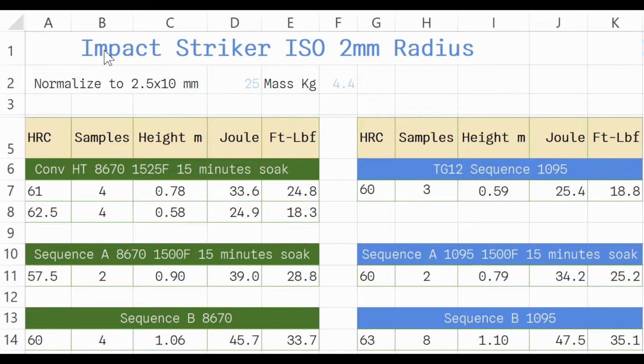I fixed the vertical impact toughness tester. Now it's using the striker, which is a carbide head with ISO geometry, which is a 2 millimeter radius. The result is normalized to this cross section here, and the mass of the striker is 4.4 kilograms.